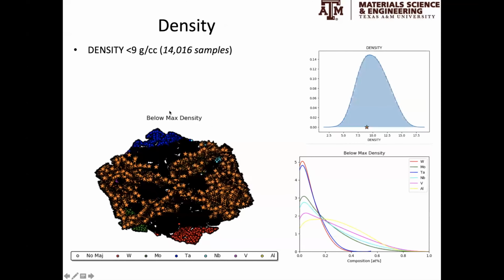This is how the density constraint looks like. It turns out that alloys with less than 9 grams per cubic centimeter are throughout the system mostly, except where you have tungsten and tantalum. And of course, you're expected to see more of these alloys where you have aluminum.